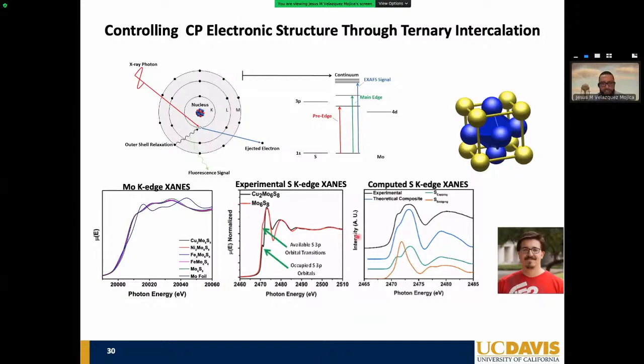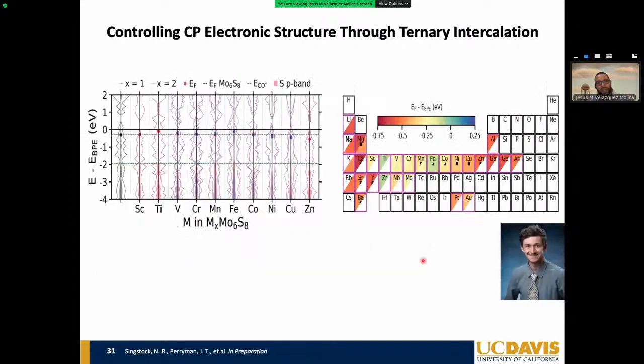These are just initial results showing you how these pre-edge features are changing as a function of the coordination of the sulfurs. What you're seeing here in orange, you see little to no pre-edge feature. Well, that's not surprising because the sulfurs depicted here in orange are all coordinated by what we like to call bridging sulfurs. However, when you look at the sulfurs here in green, these are what we're calling capping sulfurs. Those sulfurs are under-coordinated, and we believe that might be our window of opportunity to modulate charge transfer from the intercalant to available 3P sulfur orbitals and impact the binding strength of the intermediate of interest in close proximity to molybdenum.